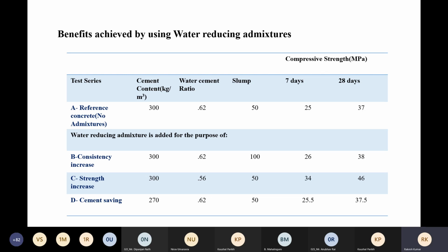After that, when we use the water reducing admixture, so consistency increases. Means cement content is same, 300. Water cement ratio is same, 0.62. But you have used the water reducing admixtures, slump increased from 50 to 100. And there is no more effect over the strength. 25 to 26, 37 to 38. Because the water cement ratio is same.